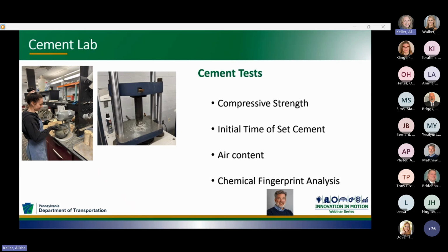Here are some of the most common tests that are done in the cement lab. Compressive strength, evaluated at 1, 3, and 7 days, is done to ensure that the cement is meeting the strength requirements in AASHTO M85 and AASHTO M240. Initial time of set is the period when cement paste starts to lose its plasticity and begins to stiffen, ensuring adequate time for mixing, placing, and compacting concrete before it hardens.